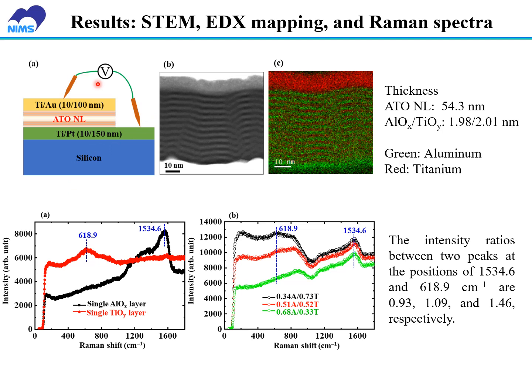Next, I will show the experimental results. This figure shows the schematic diagram of the capacitor. We measure the surface metal and the bottom metal for the electrical properties. Based on the STEM and EDX mapping, we can conclude that the ATO nanolaminate has been fabricated on the silicon substrate successfully.